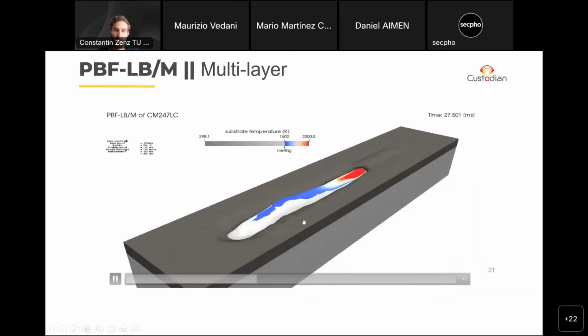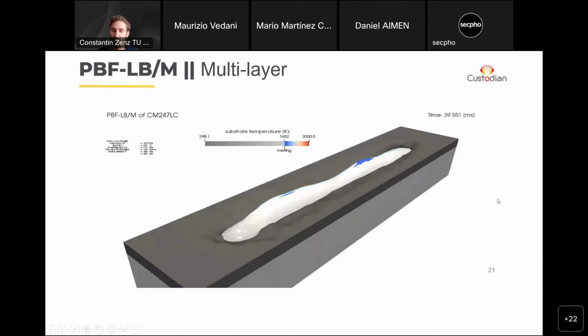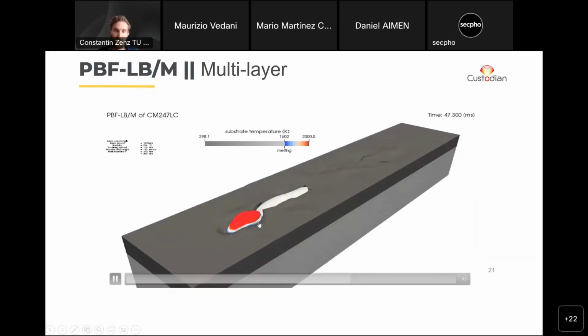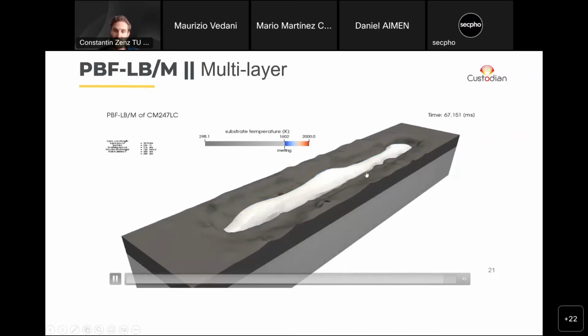So you can see here, after each layer where we scan 2 tracks, we add some more powder. And this is also possible within the continuum mechanics approach that we developed here. Here we can see, because of the previous melt track, we see some irregularities because of the unidirectional scanning strategy. And then we see that actually the weld speed is too high to be fully covered by the next powder layer. So this is something that could be already seen in a simulation, so that we do not face these problems then in an experiment later.